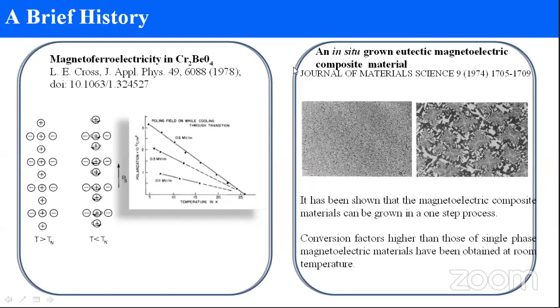Okay, so this is one of the first reported single phase magnetoelectric materials, around the Néel temperature, around 25 Kelvin. The dielectric constant shows some anomaly here. Okay, so that means that you are having a coupling between your magnetic order and your electric polarization. Okay, actually this is an antiferromagnetic material. This is not a ferromagnetic material, and the Néel temperature is around 25 Kelvin. So even then it has that kind of coupling. So we call this a magnetoelectric material.